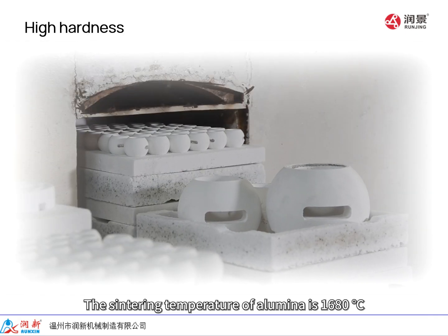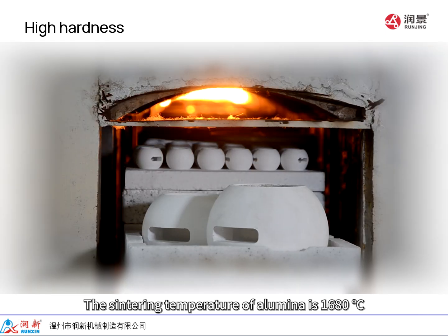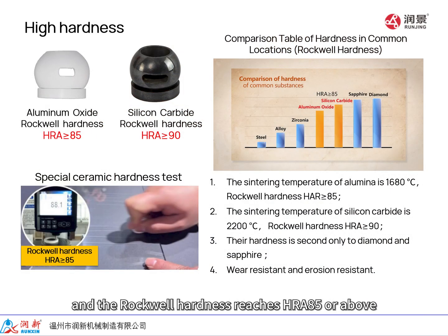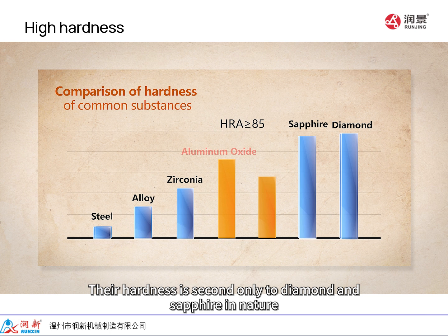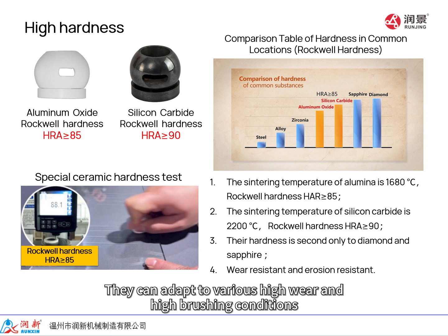The sintering temperature of alumina is 1680 degrees Celsius, and the Rockwell hardness reaches HRA 85 or above. The sintering temperature of silicon carbide is 2200 degrees Celsius, and the Rockwell hardness reaches HRA 90 or above. Their hardness is second only to diamond and sapphire in nature, and is 7 to 9 times that of steel. They can adapt to various high wear and high brushing conditions.